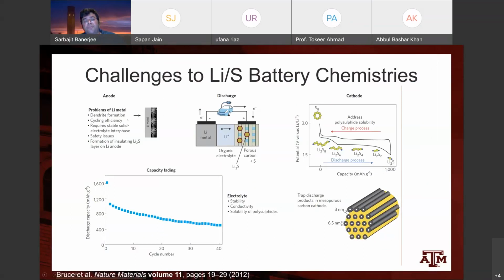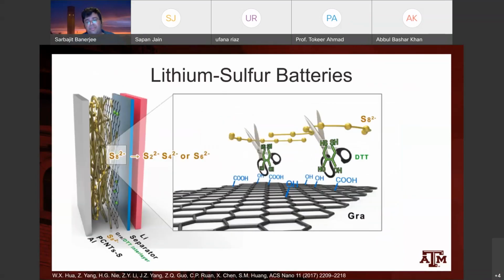The problems of lithium metal dendrite formation, having good cyclic efficiency, the formation of these insulating lithium sulfide layers from the polysulfide shuttle, the polysulfide being transported across, and then having a good SEI layer, and then the safety issues of the dendrite, finding a good electrolyte that is stable across this window, and that doesn't have very high solubility for these polysulfides to dissolve them, and then to be able to trap these discharged products, including the soluble ones, and to prevent them from getting into the electrolyte or going over to the anode. So lots of different strategies, again, from the perspective of functional materials.